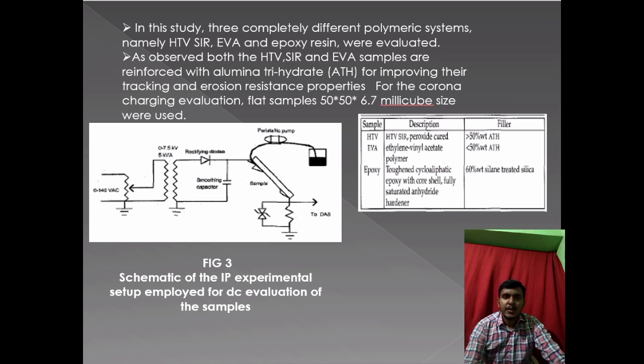Then coming to tracking and erosion resistance, it was evaluated in an inclined plane test setup, which is known as IPT setup. For DC evaluation, a single phase half cycle diode rectifier was assembled and connected to the output of a transformer from 0 to 7.5 kV, rated for 5 kVA, to supply DC power, and a 2 microfarad smoothing capacitor was connected for filtering purpose. With all the above parameters, a voltage drop not higher than 10% is expected for a current of 100 milliamps flowing through the high voltage circuit.